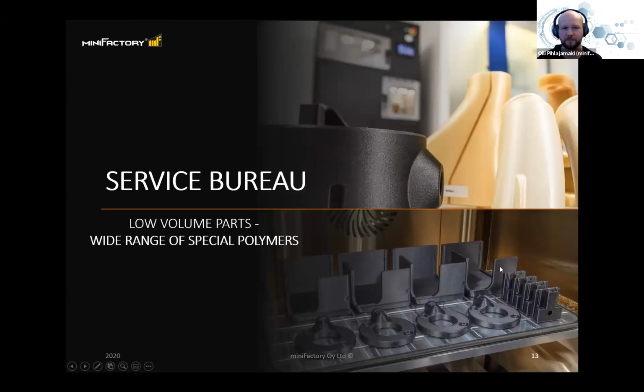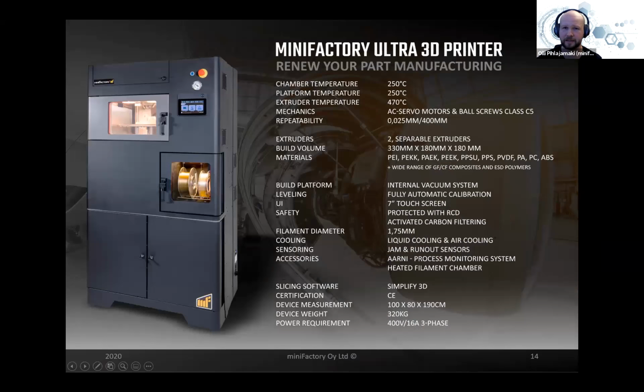Then of course, service bureau, based on the fact that when it comes to thermoplastics, miniFactory Ultra has the widest material range available on the market. And the reason for that is the chamber temperature. So the whole chamber can be heated up to 250 degrees, which allows us to print the most demanding polymers and polymers with the highest glass transition temperatures. So with this heated and controlled temperature, we can control the parts perfectly during the process to avoid all the internal stresses and to ensure optimal mechanical properties for printed parts.